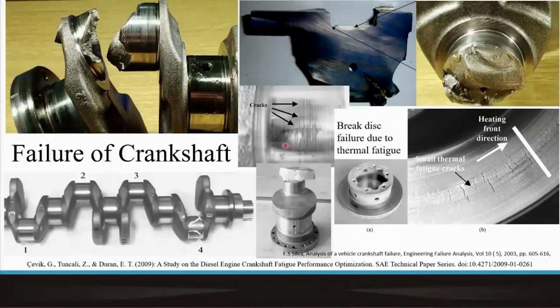In fact, these kinds of cracks typically happen when you see such marks or deformation marks developing onto the surface, which eventually get concentrated at particular regions. And if the stress concentration becomes too large and crosses the fracture limit, then micro cracks develop, then they combine, and when the micro cracks combine, that leads to a larger crack opening, which can lead to a catastrophic failure. So similar cracks you are seeing here on the top surface.